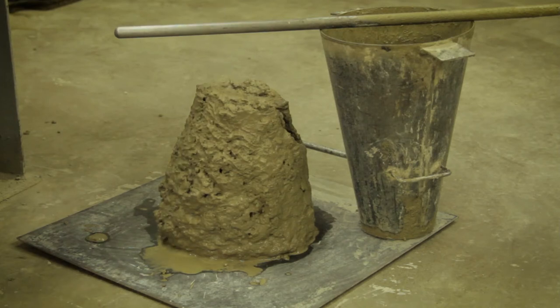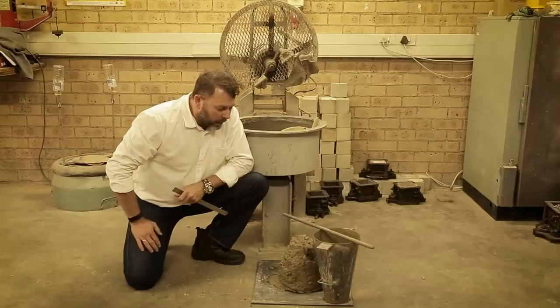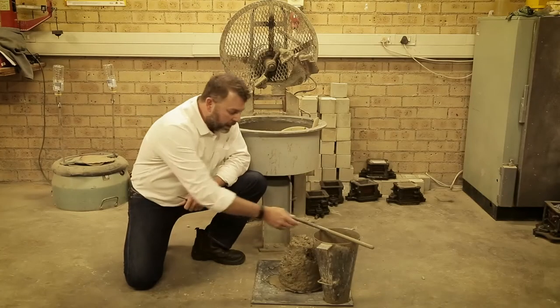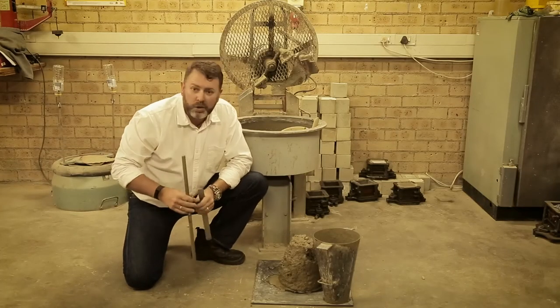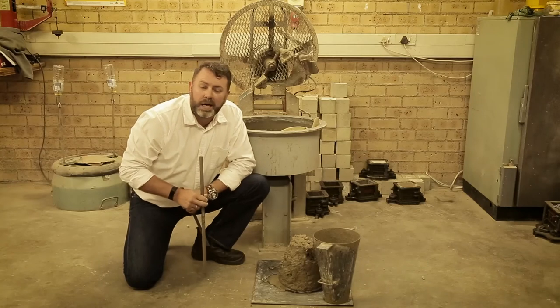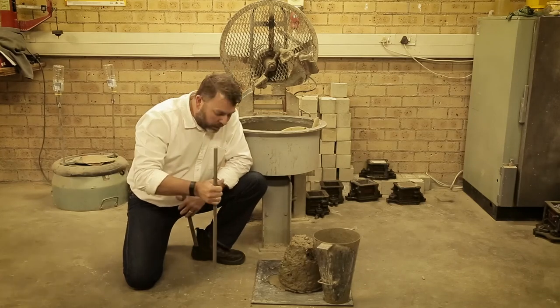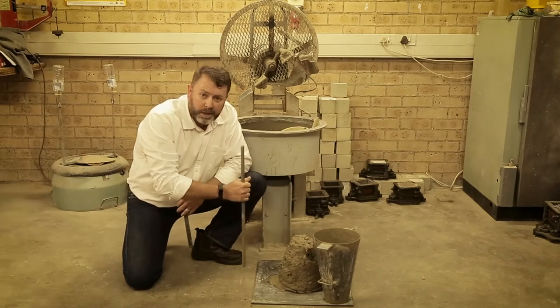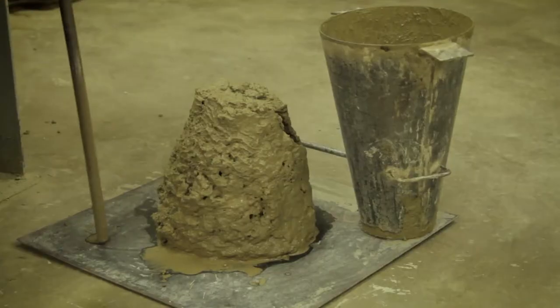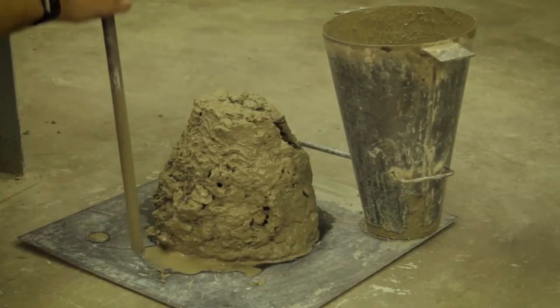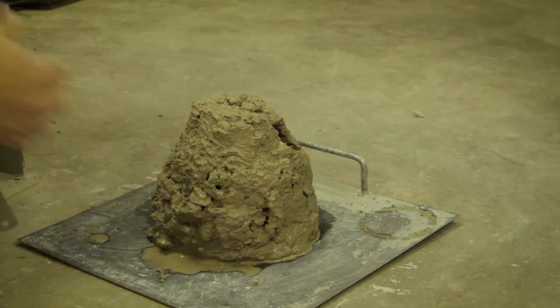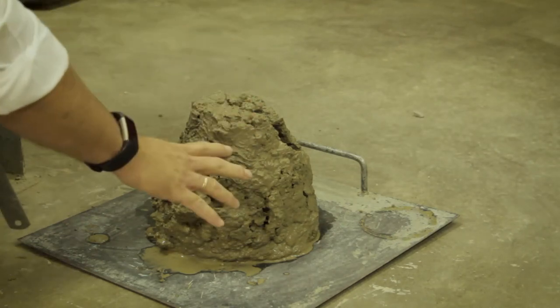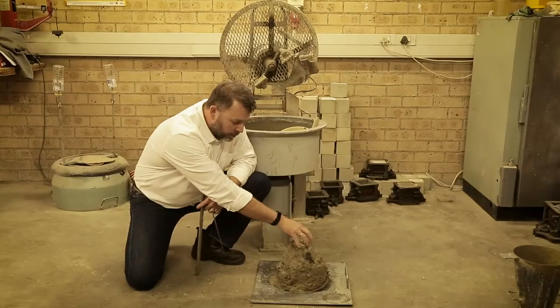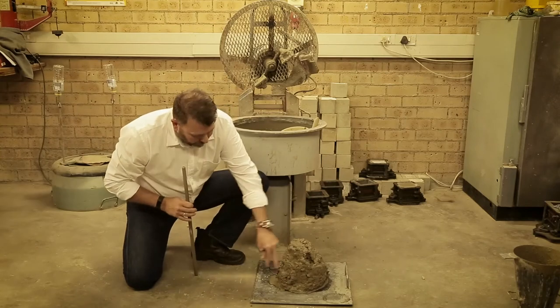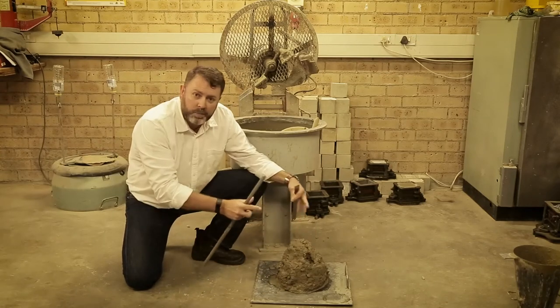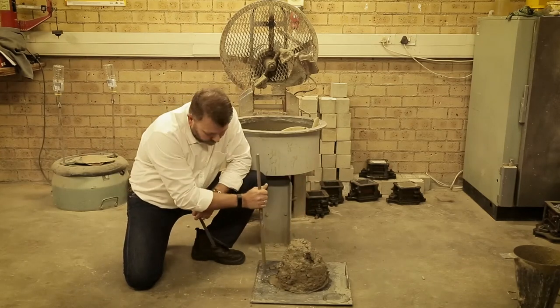Also remember that there is more to a slump test than just the value. From the slump test, you can also assess workability and the cohesiveness of the concrete. We do that by tapping the base plate as follows. While we tap the base plate, observe how the concrete moves. You can see that the top ring stays intact and the bottom part of the concrete is going to become progressively larger.